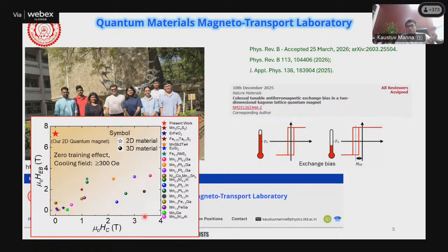In most compounds, the coercive field is very high. If you want practical application, the ideal is that the coercive field should be very low so that you can do antiferromagnetic spintronics, and the exchange bias field should be very high. We have found that the best 2D material ever reported is Fe1/3NbS2. These stars are actually 2D materials. This is an intercalated compound, so it is very difficult to control the composition. And the highest for a 3D material is around 3.3 Tesla.